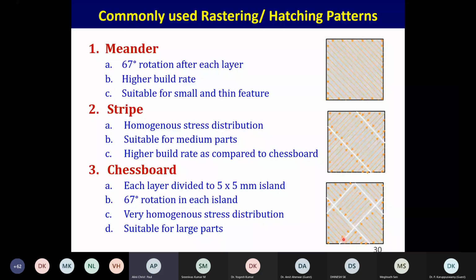Another way people try to work on to reduce this sort of distortion is to fill the area with a Meander pattern. What you are doing is you are depositing in this direction. After that, you are rotating the whole geometry by 67 degrees and depositing like this. So in every layer, you are rotating your rastering pattern by 67 degrees, which is called the Meander approach, and this is very nice and somehow balances the effect of distortion and deformation.